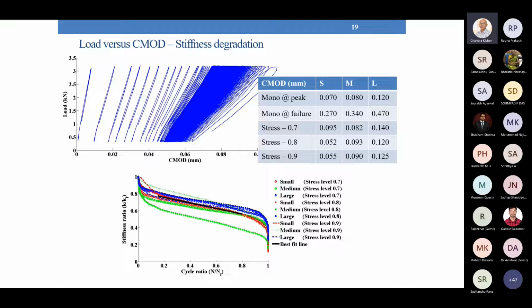In the degradation of the stiffness, the slopes are all the same, for different stress levels and for different sizes of specimen. So what it means is we can use this rate of degradation as a material property, in order to develop fatigue laws.